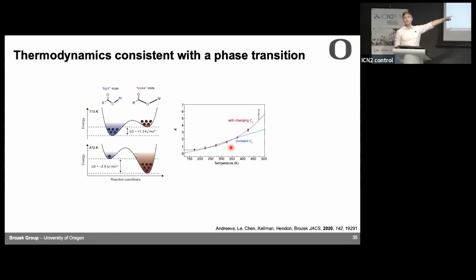When you do that, you get the curve that I'm showing in blue. It's not a very good fit. And that was surprising. And so we were looking around for other ways to fit the data. And it turns out that you can change the Van 't Hoff equation a little bit and allow the specific heat of your material to change. When we do that, you get the curve in pink and it fits much better. But why would you let the specific heat change?